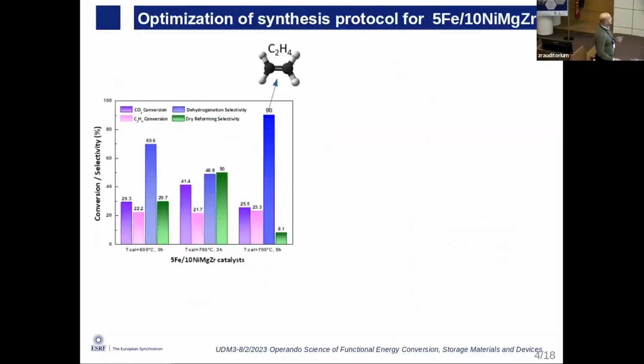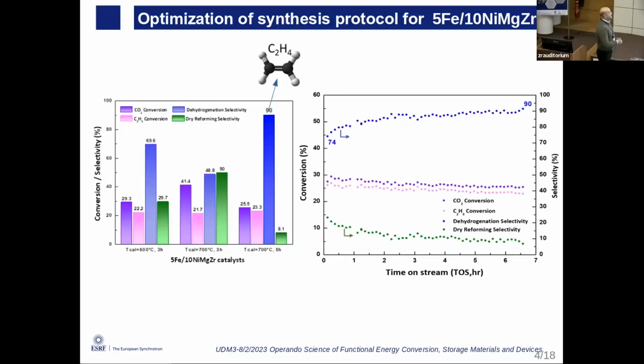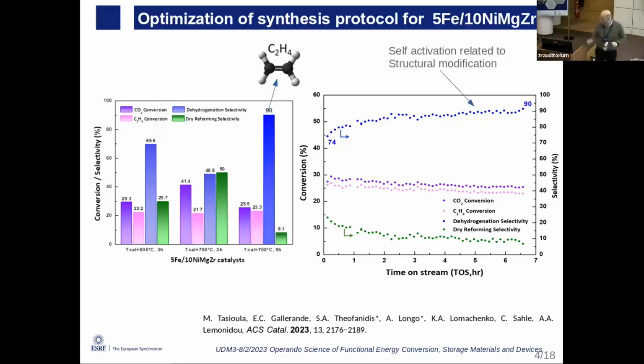But if you look at the performance, it's clear that the best catalyst is the one obtained at 700 degrees for 5 hours. That has a selectivity for the production of ethylene of 90%, which is quite impressive. In addition, the side carbon scission reactions, typically what happens in dry reforming of ethane, are completely damped down, so a very low amount. This is very interesting, but even more interesting is that if we look at the conversion as a function of time on stream, sorry, we do see that there is a strong increase.